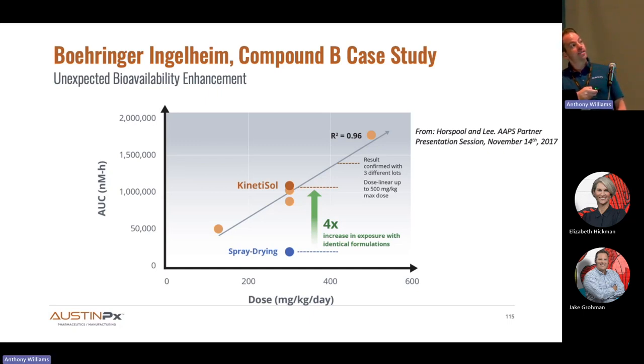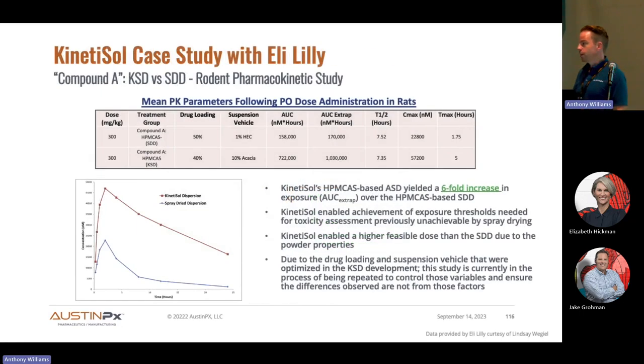And more than that, they were able to escalate the dose well above the maximum dose they were able to administer from spray drying. This was presented in 2017 by Keith Horspool, who was VP at Boehringer Ingelheim at the time, and he presented several case studies. This was one of the first ones, but he said this was important to the company because it allowed them to identify tox issues that wouldn't have been otherwise identified, and they killed the drug. He estimated it saved the company about $10 million, avoiding clinical failure.